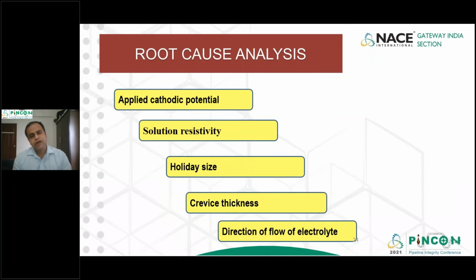So, what are the 5 different root causes that I could identify with my work? First is the applied cathodic potential, the impact of it. Second is the resistivity of the solution which is there in and around the pipe. The holiday size matters a lot for the coating. And finally, the crevice thickness also matters a lot. In my case, it did. Direction of flow of electrolyte is a matter of concern, but we don't have any control over it.